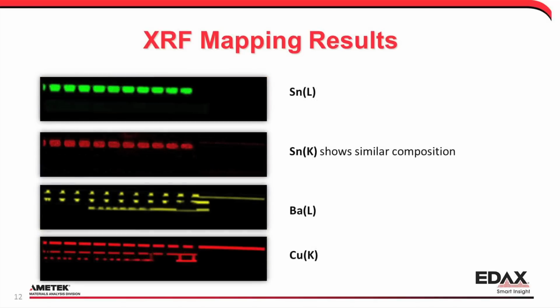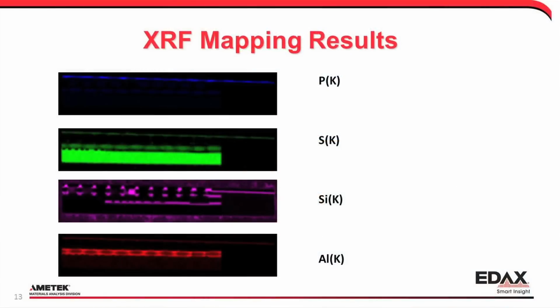Sometimes the L line and K line are not really all that different, which is probably telling you that throughout the depth of the sample, it doesn't really change in distribution or area. And that's pretty much what we see with the tin L and the tin K, pretty much exclusively in those kind of hot spots there, although we do see a little bit of extra tin in some areas, mostly similar. We have barium L and copper K, and just added some additional elements to fill in the rest of the picture, basically.